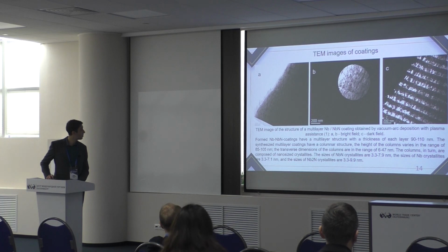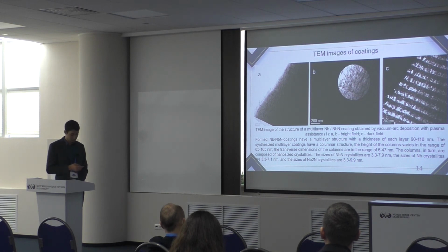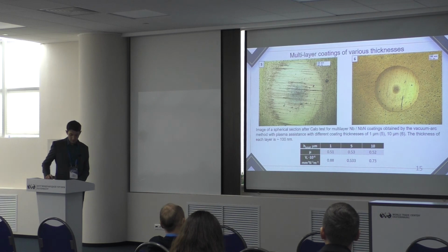The synthesized multilayer coatings have a columnar structure, and the columns in turn are composed of nano-sized crystallites. It was found that niobium nitride coatings of different thickness have similar tribological characteristics to the coatings with 5 micrometers thickness.